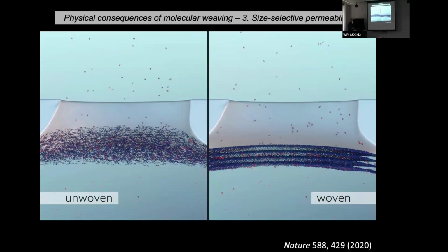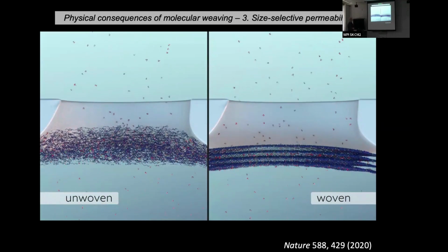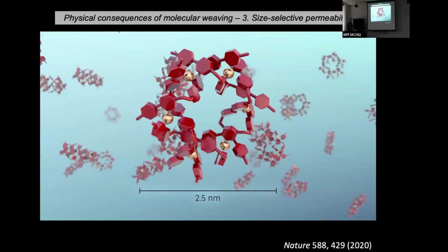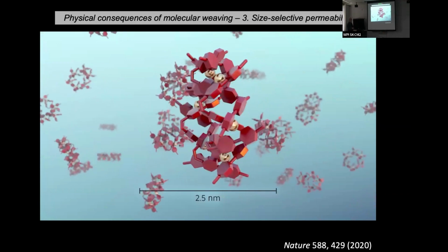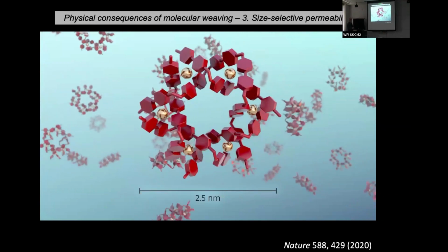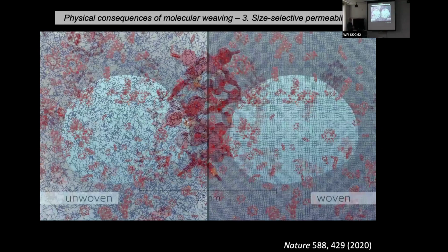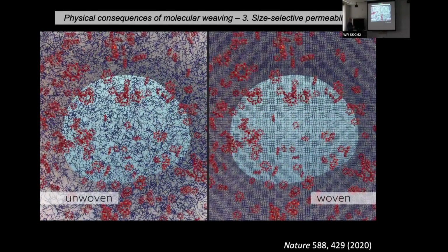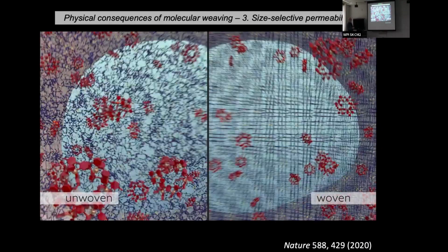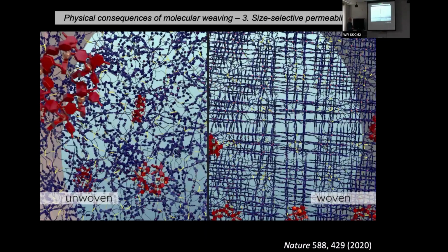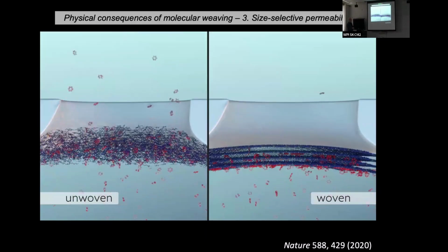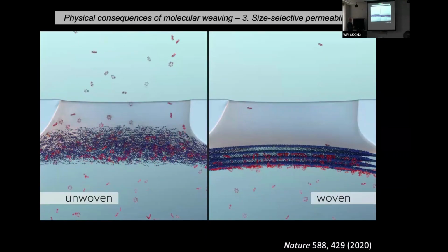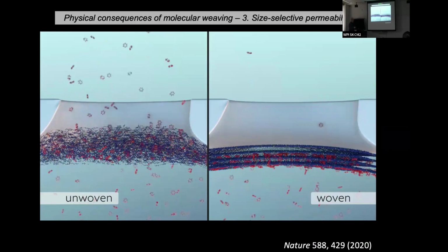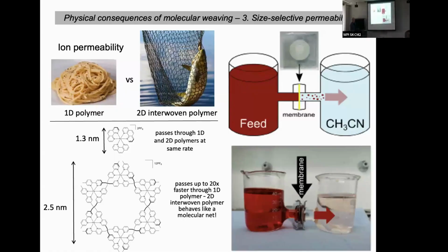But if we take the larger colored metal complex, this is 2.5 nanometers, so it's bigger than the holes in the net. It can still pass through the holes that we see in the 1D polymer, but it's trapped in the holes in the 2D woven polymer. And we see a much slower rate of passing of the dye through those systems.